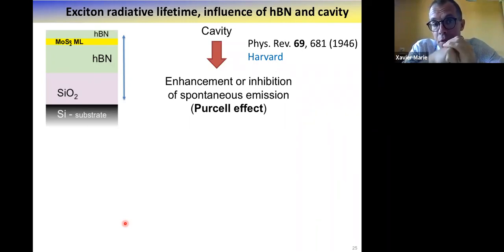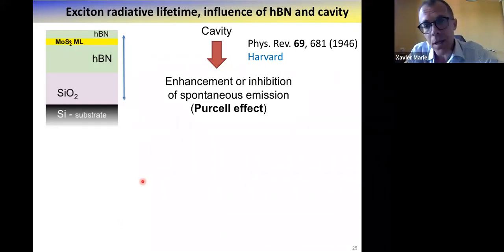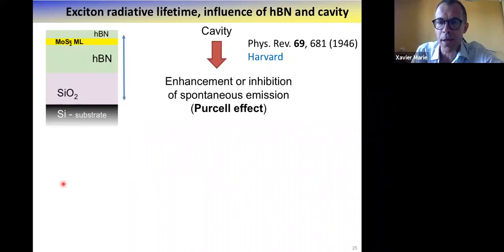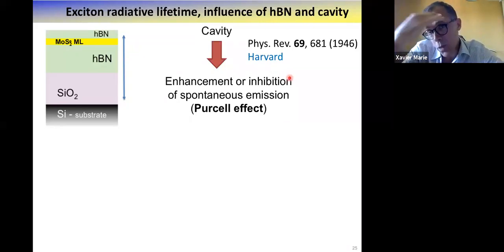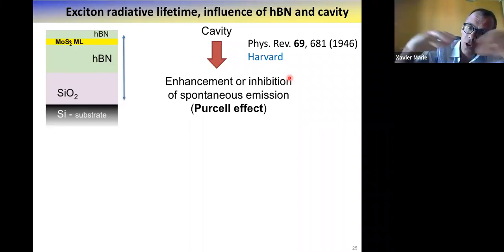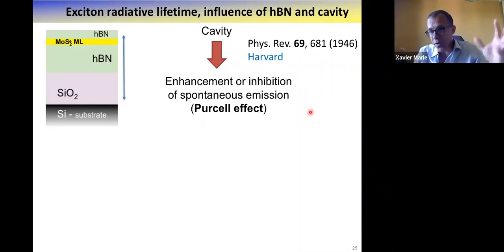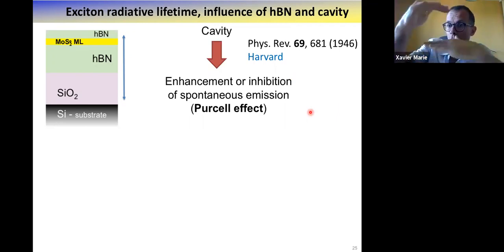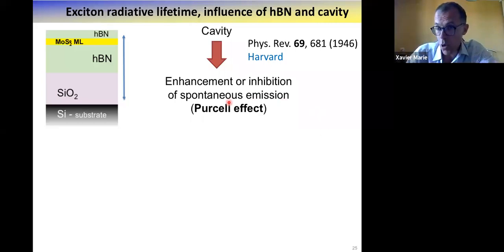In fact, now we have a further confirmation that indeed it was a radiative recombination, because we can fabricate van der Waals heterostructures where we can control this radiative recombination through a Purcell effect. So I don't know if you are familiar with this kind of effect. It's well known in atomic physics, following the pioneering work of Purcell. It is when the spontaneous emission time of an excited electronic system depends on the fluctuation of the surrounding environment and the quantum field fluctuation. So if you place your emitter close to a mirror or in a cavity in a weak coupling regime, you can control the spectral density of this fluctuation. And so, depending on the position of the emitter with respect to your mirror, you can either enhance or inhibit the spontaneous emission time.